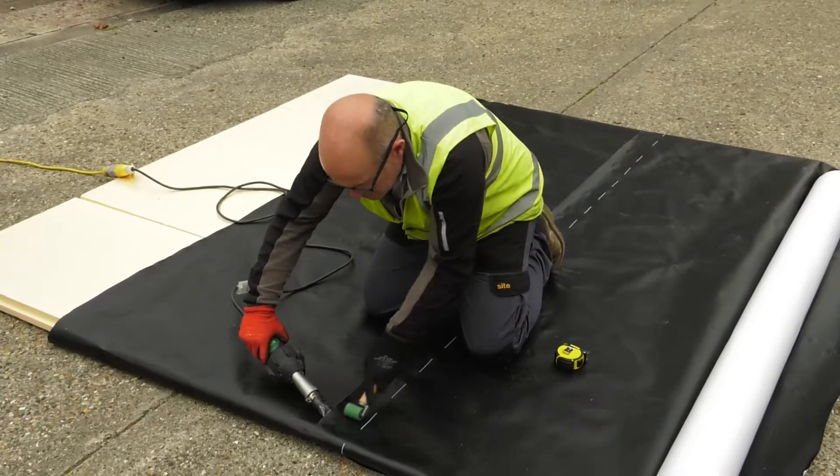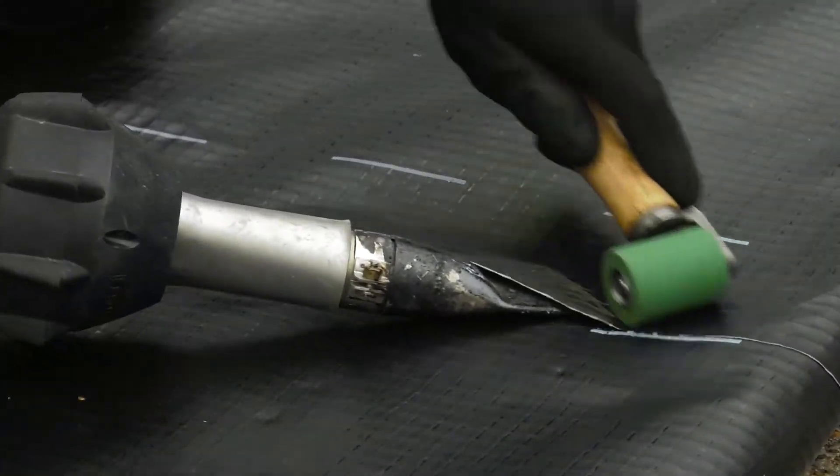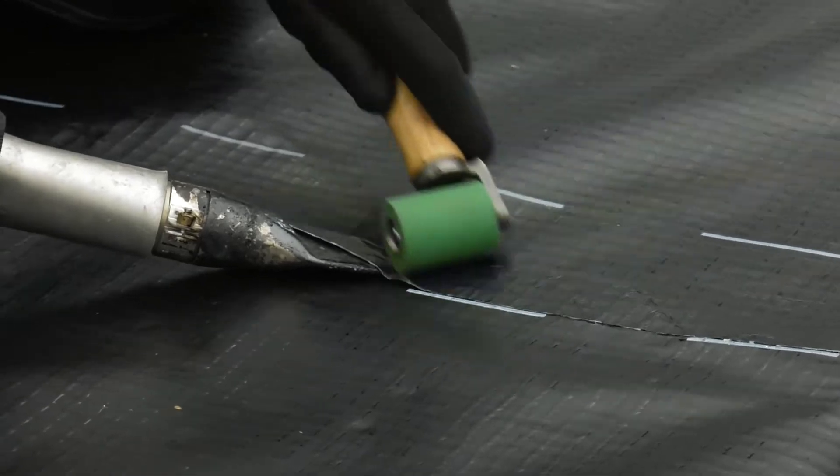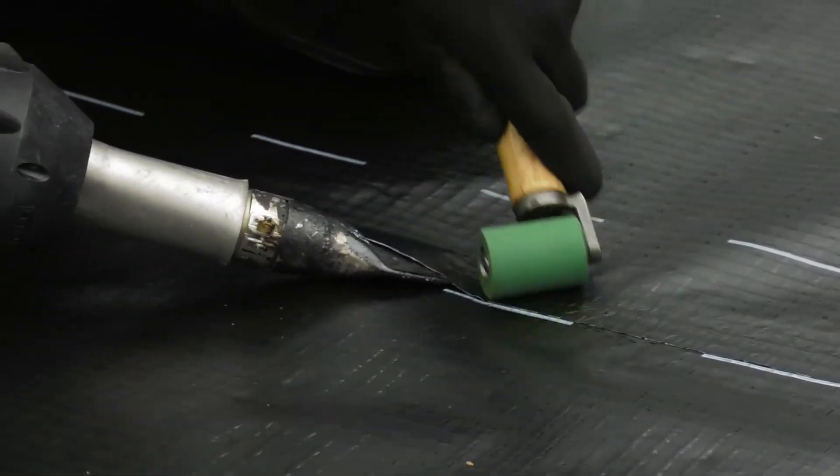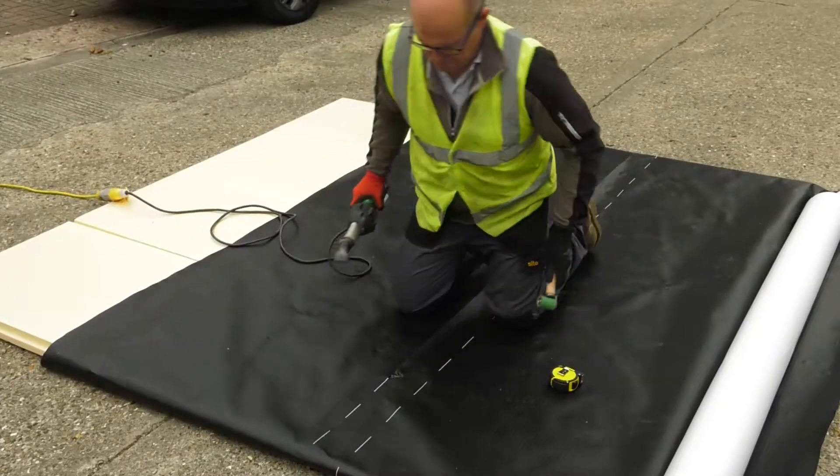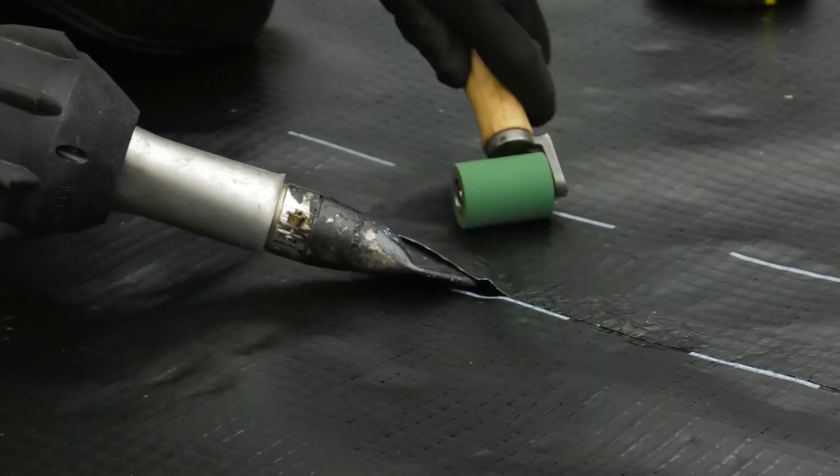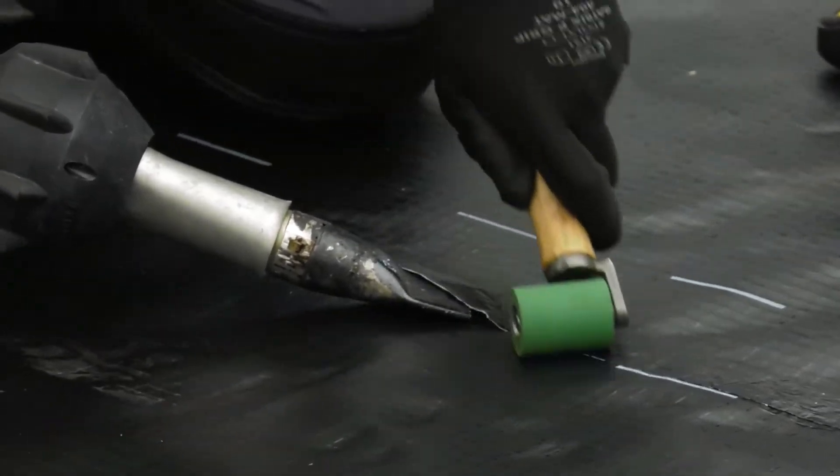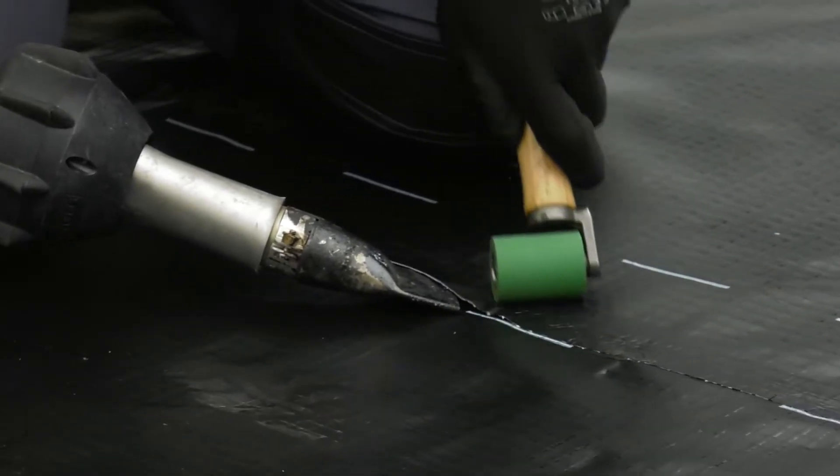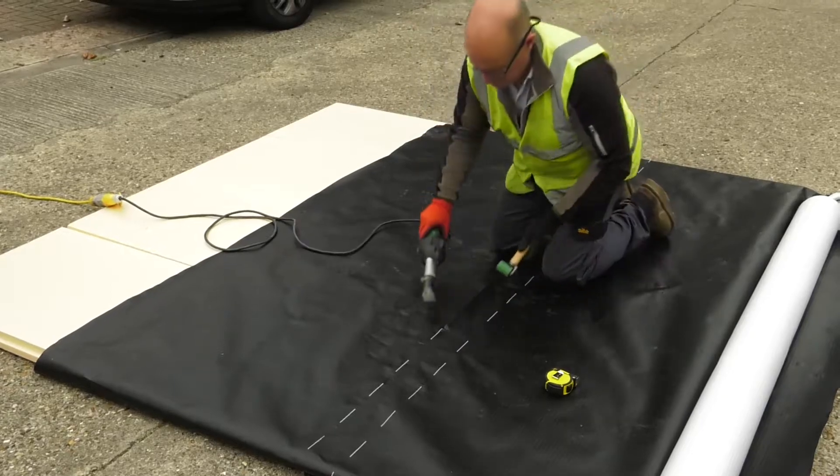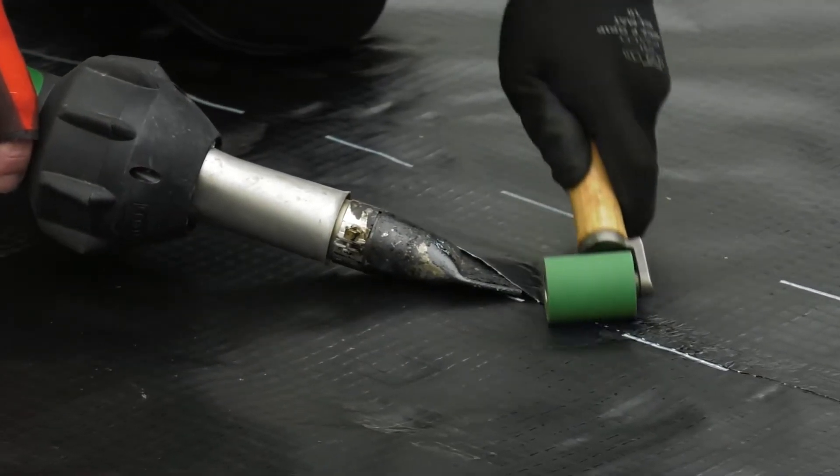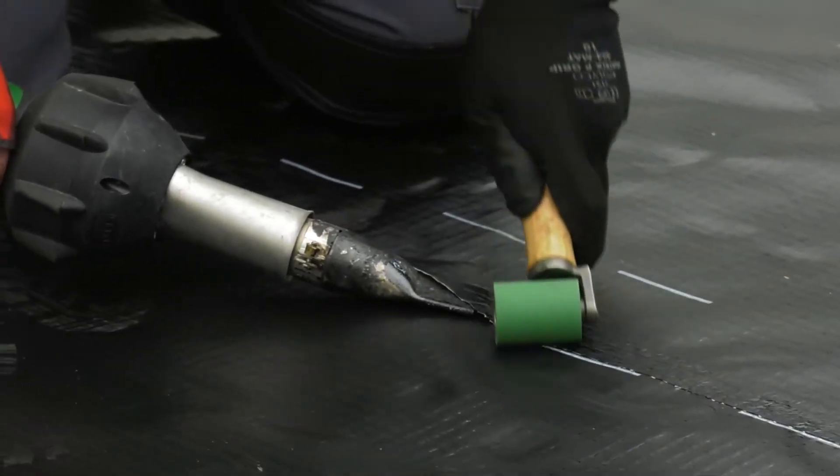Now we can move to the main seam, where we will place the nozzle between the sheets as we did in the test seam. Continuously angle the nozzle at 45 degrees, keeping the roller adjacent to the nozzle to trap all the air that has been passed through the nozzle. This will activate the seam. Sometimes membranes are spotted to keep them in position, or weighting down the membrane should be considered. Also, be sure to maintain the 100mm margin that has been specified. In this particular product, it can be identified by the dotted lines and is one of the requirements the technician must achieve during the course of their installation.